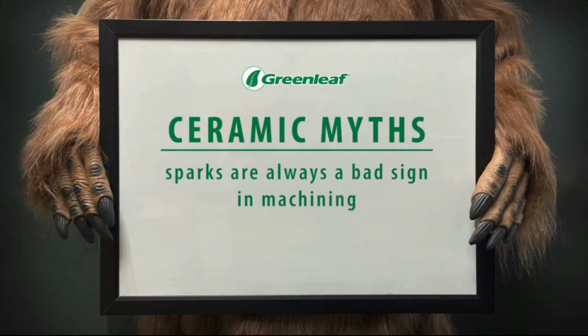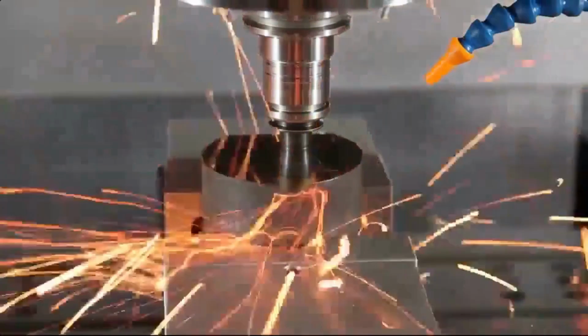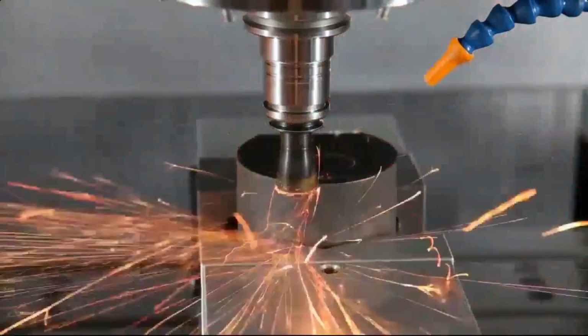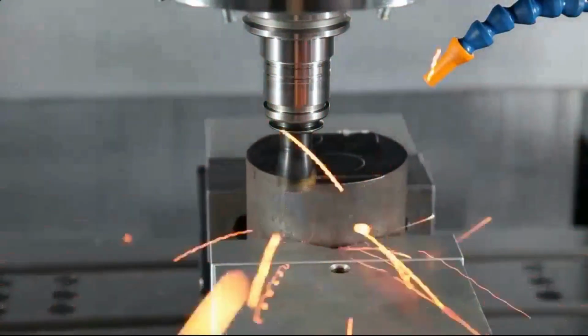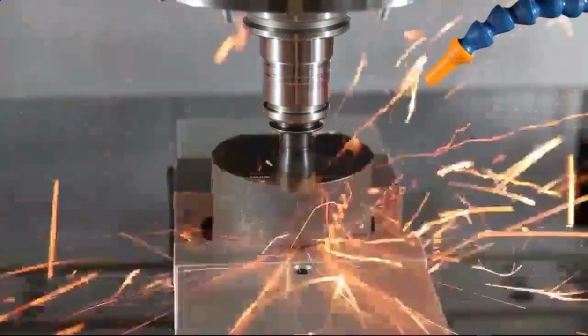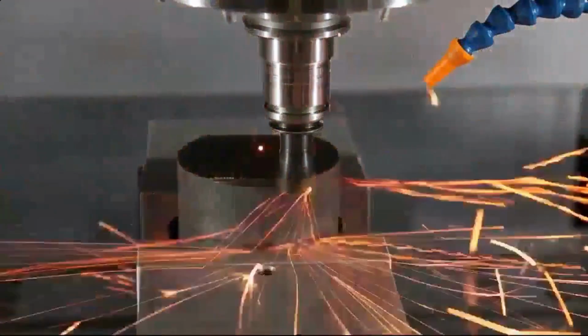So when you're machining, sparking can definitely be a sign that something isn't right. However, when the process is optimized with ceramic tooling, what you are actually seeing are red-hot chips, not sparks. Sparking can still be a sign that something isn't right, but the red-hot chips you are seeing are no cause for concern. All tools actually generate heat during the shearing action to remove material.